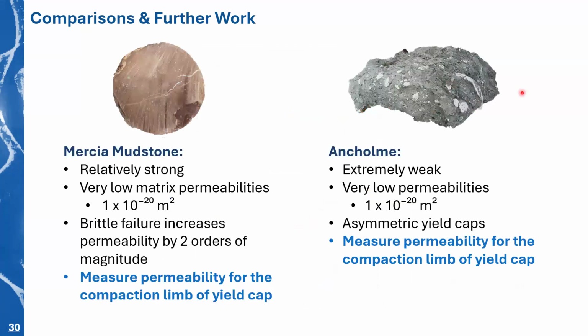So to compare the two, we found that the Mercia mudstone is relatively strong for a mudstone. It's got very low permeabilities when it's intact, but once it's broken, once it brittly fails, permeability increases by 2 orders of magnitude. For the Ancholme Group, it's the opposite. It's extremely weak, but it also has very low permeabilities, and it maintains the low permeabilities after it yields.